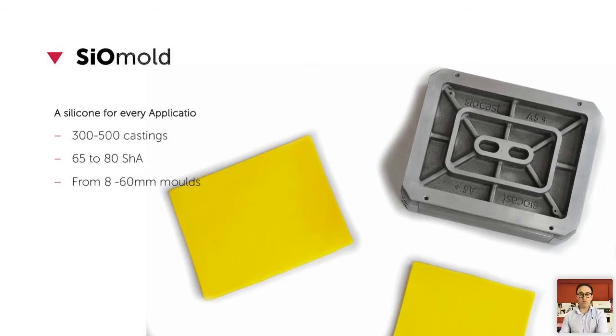This silicone is extremely performant. We can do between 300 to 500 castings with every mold. That means that it's more than 10 times the life expectancy that you have with other silicones for vacuum casting or resin spin casting. When we talk about 300, 500, it depends on the complexity of the parts; you may have a lower life expectancy of the mold over time. But in general, we can see between 300 to 500 castings, okay?